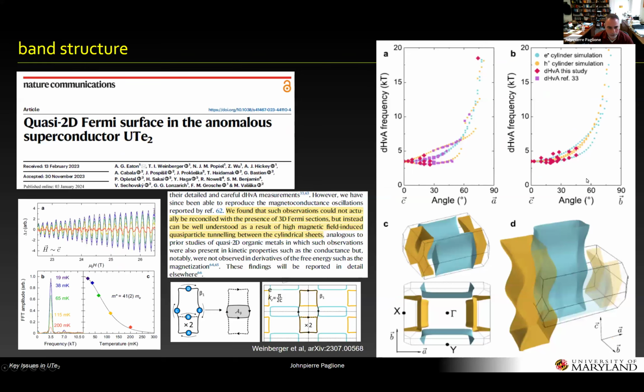And then more work by the Cambridge group has a different interpretation. So they also see, at least through some angle range, I'm sorry, I'm not sure if I'm pointing to the right data here. They do, at least I know, they do see through some angle range these small pockets, but they claim that the data is more consistent with a breakdown model where there's some orbits that jump across the calculated Fermi surface.